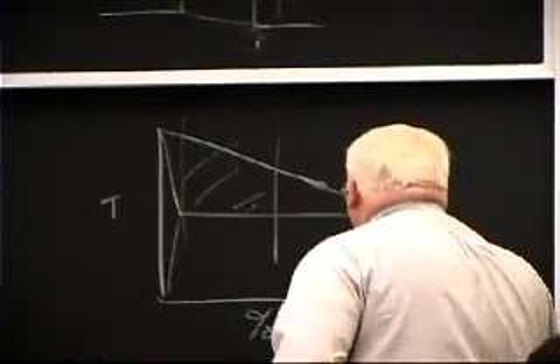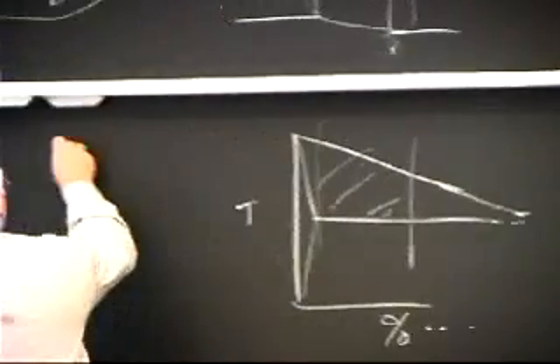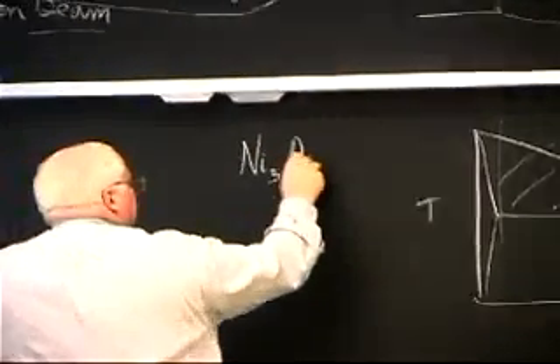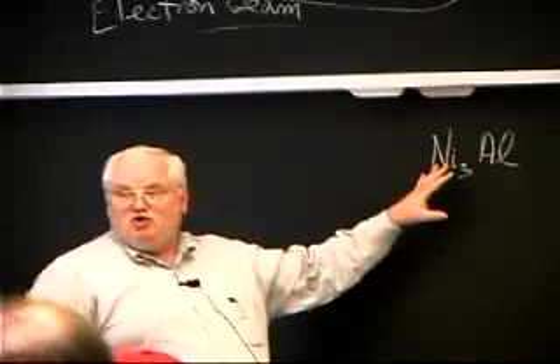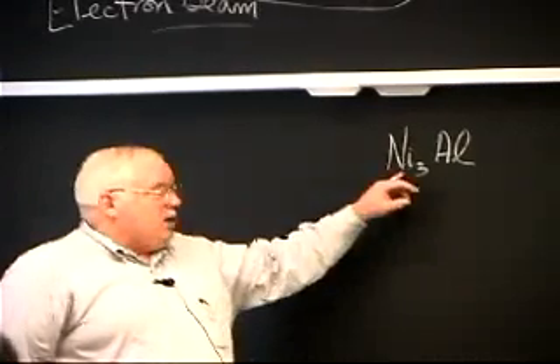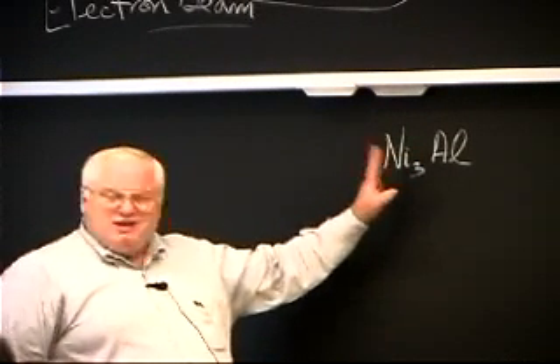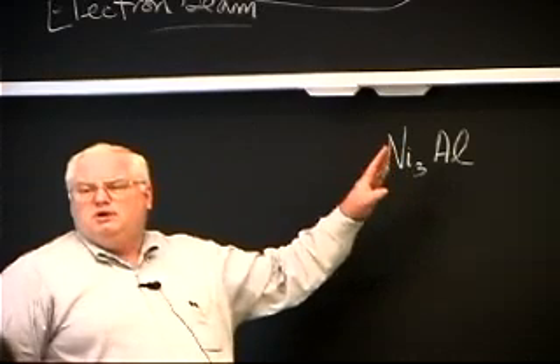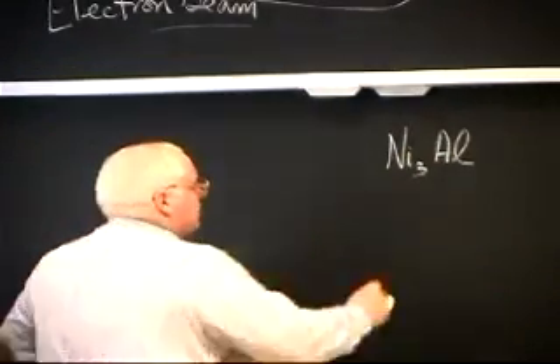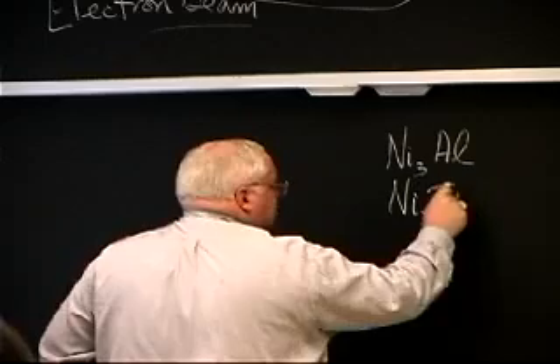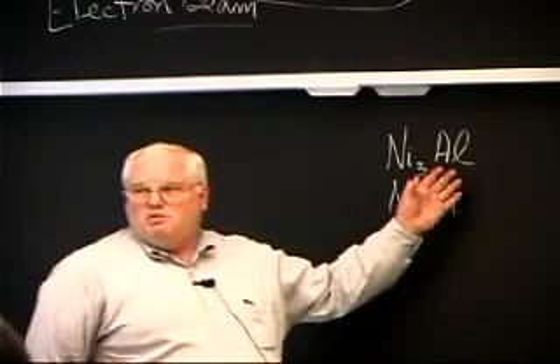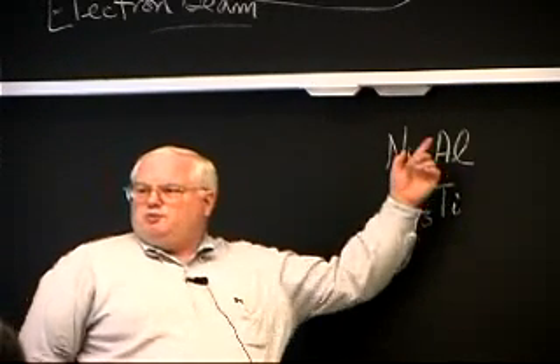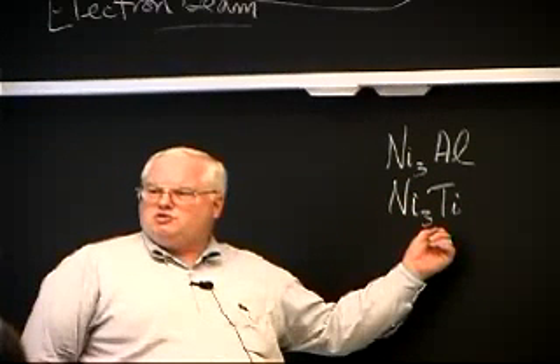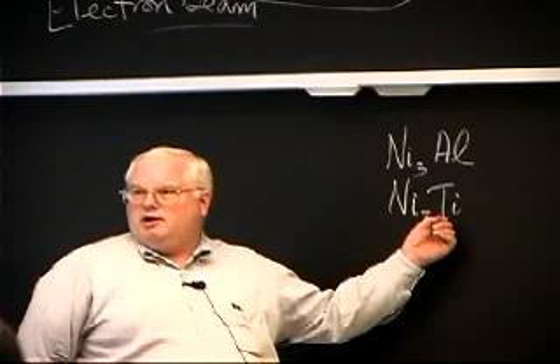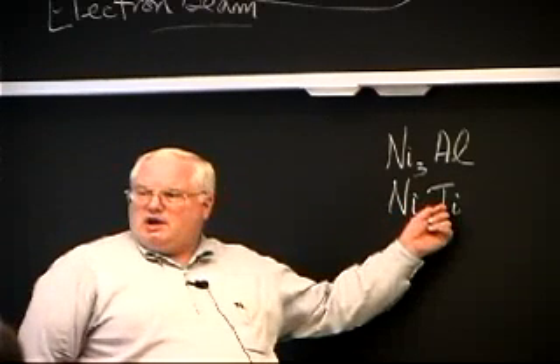The problems for the high temperature alloys are that you typically have nickel-3 aluminum. Now you have aluminum in there and it forms this gamma prime phase, which has wonderful high temperature properties. The problem is it cracks big time. You really cannot weld a high aluminum nickel superalloy. And so what they do is they change that and use titanium, and there are actual plots you can go to for weldability, and you basically look at the aluminum titanium ratio. And the more aluminum that's replaced with titanium, the more weldable the alloy is. Direct correlation. Less cracking with titanium than aluminum.